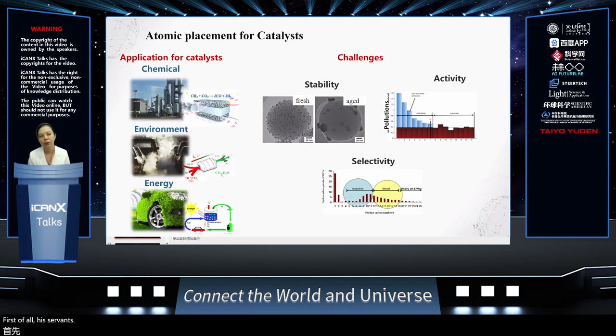First of all, the stability issues. They tend to agglomerate through aging because they're so tiny. So we want to really confine them and anchor them. That's the strategy for stability. The other one is activity. Activity is definitely a very important factor for heterogeneous catalysis, and interfaces definitely play an important role in how we can promote it. And the third one is selectivity. For a lot of chemical synthesis, reactions may happen very well on one side, but a side reaction may happen on the other side. As I just showed you about selective deposition, this kind of thing would help to improve the selectivity.